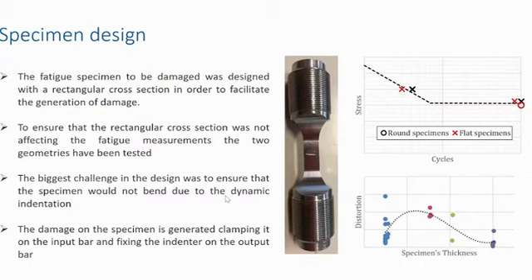Then we pass to the design of the specimen. We designed the fatigue specimen with a rectangular cross section in order to have a flat surface where to perform the damage. We made sure that this geometry didn't affect the fatigue life, testing both types of geometry, the classical round one and the one with the rectangular cross section. And then a problem that we were having was the distortion of the specimen during dynamic indentation, which is a problem found in literature, where people usually perform the indentation statically, or they flip the specimen and perform another one to put it back.